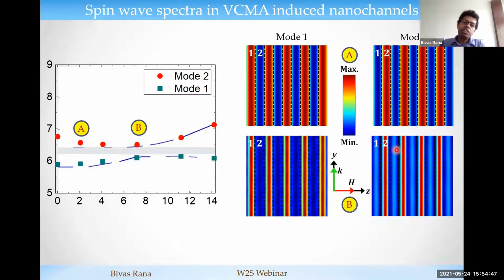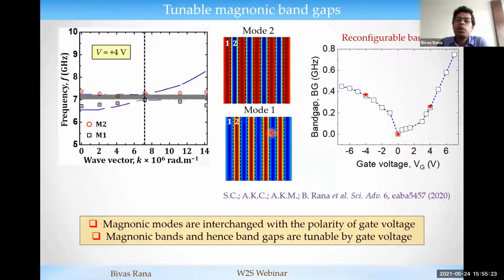The most probable reason behind this is the repulsion between mode 1 and mode 2, which are propagating in channel 1 and channel 2. That's why you can see this kind of very nice behavior, because below this wave vector the spin wave dispersions for mode 1 and mode 2 are quite different, and then the dispersion character is changing, and the slope is changing, probably due to the repulsion of the spin waves propagating through channel 1 and channel 2. And the most important feature is the reconfigurable property.